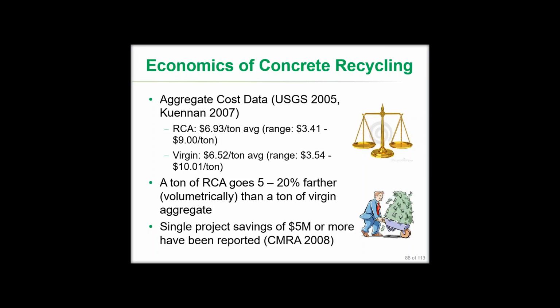Applied cost data, as you can see, going back again 8 to 10 years, comparable numbers, and these are overall averages, and there's a wide range with each. The averages are pretty comparable at that time, $6 to $7 per ton for both materials, but it's worth noting that a ton of recycled concrete goes farther volumetrically than does a ton of virgin aggregate because of the lower specific gravity. You've got your natural aggregate particles that are included there, but you have a significant amount of clinging mortar onto the outside of those aggregate particles, which is a much lower specific gravity.